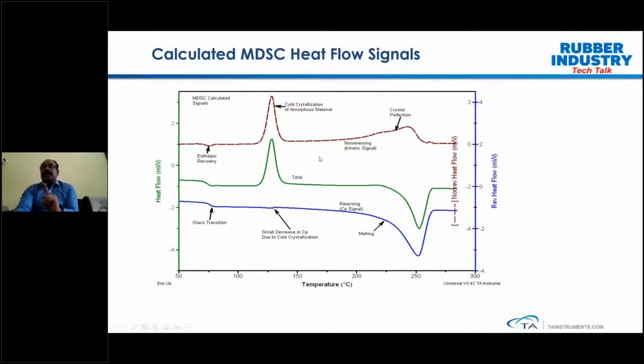So if you closely look at the thermogram of each individual heat flow signal, you can see the total heat flow, the green one, carries all the information. For example, in this case, we can see clearly the step change followed by cold crystallization and then melting. The reversible heat flow basically shows only the transitions which are reversible or thermodynamic in nature, like the glass transition temperature and melting point. These are the thermodynamic events which are easily measurable.